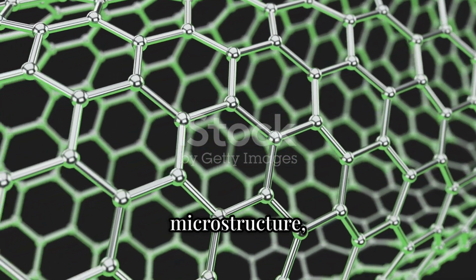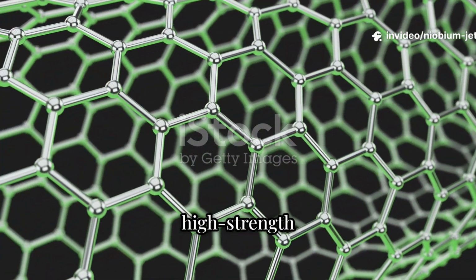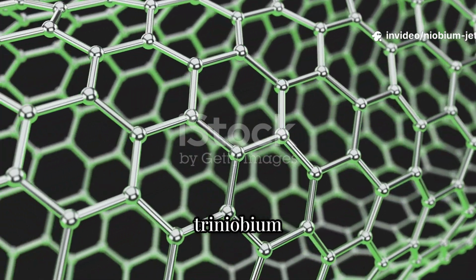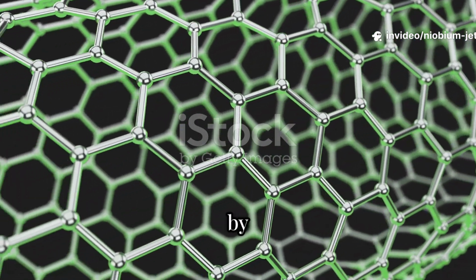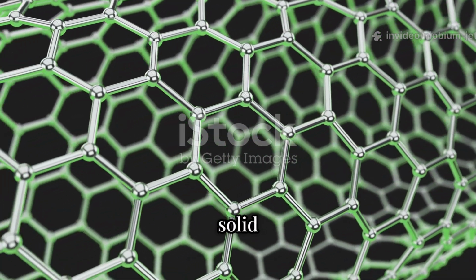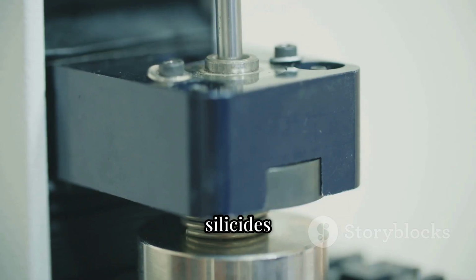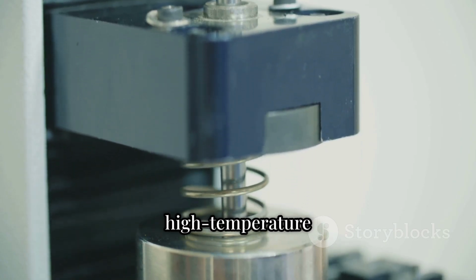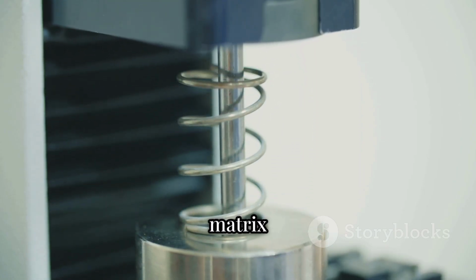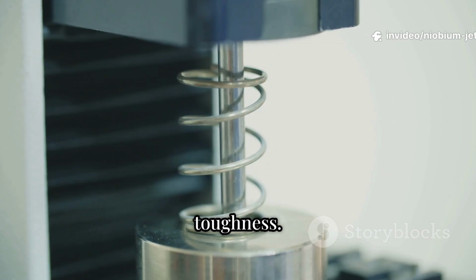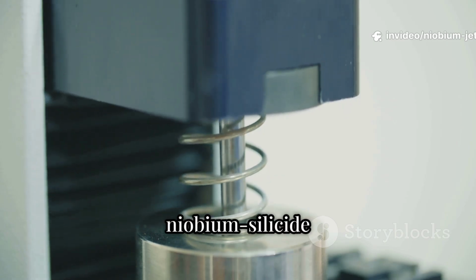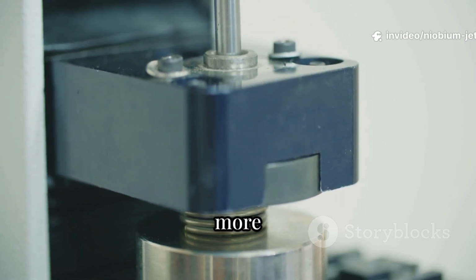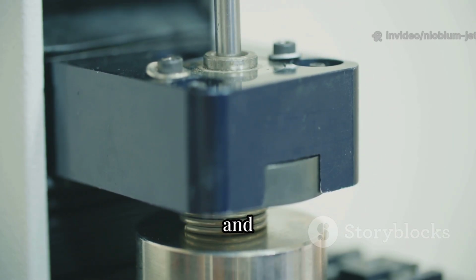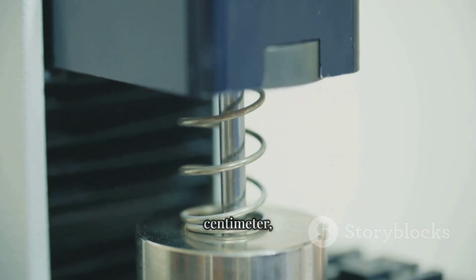The key is their microstructure, which is composed of high-strength silicides, such as triniobium pentasilicide, reinforced by a ductile niobium-based solid solution. The silicides are primarily responsible for high-temperature stiffness, while the niobium matrix provides the necessary toughness. A crucial advantage is that these niobium-silicide alloys exhibit more appropriate densities between 6.6 and 7.2 grams per cubic centimeter